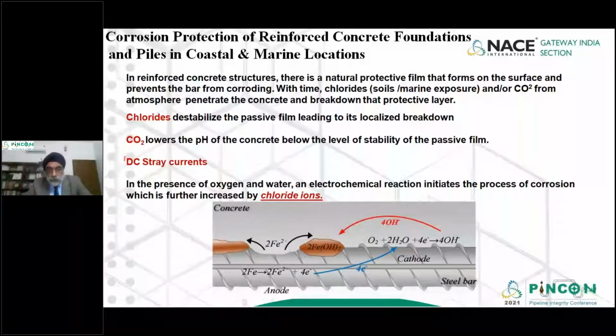The third element in refineries which can cause corrosion on the rebars is DC stray currents. As I said, now in refineries, cathodic protection of buried piping has become prevalent. Now, while protecting the buried piping in a refinery or in a petrochemical environment, we can cause DC stray current corrosion on concrete reinforcements which are near the anodic gradients. So if proper design is not done of the cathodic protection of the plant piping, it can endanger the concrete piles, the pile caps, which would be in the anodic gradient of these anodes.